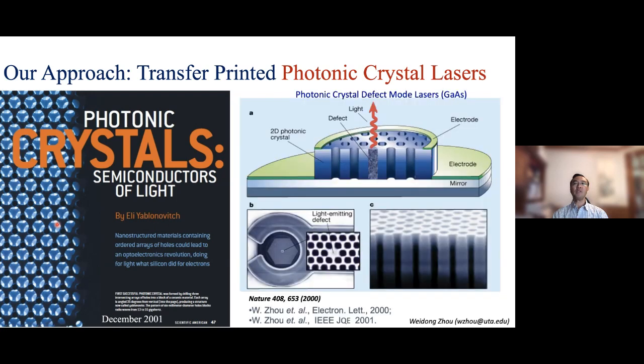So the idea here is basically to have this kind of periodic structure drilled into the dielectric material to manipulate the photons. And luckily, when I was a student at Michigan, we were working on this kind of very exciting front-edge research area early on, where we were one of the first groups to demonstrate the electrically pumped photonic crystal defect mode laser on gallium arsenide, the compound semiconductor material. So that was one of the major breakthroughs then.